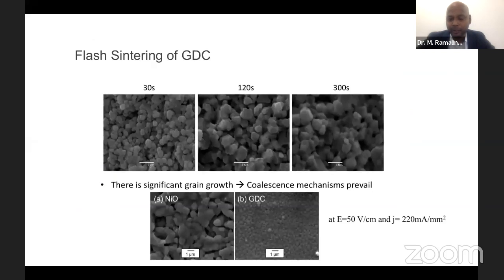Due to the flash sintering technique, which is a new technique for sintering, we can make sintered nanomaterial within 5 minutes. Within 5 minutes we can sinter the materials very fast. Even I can say minutes.